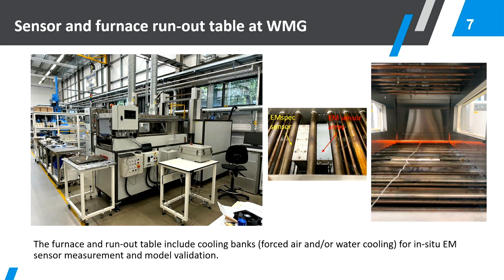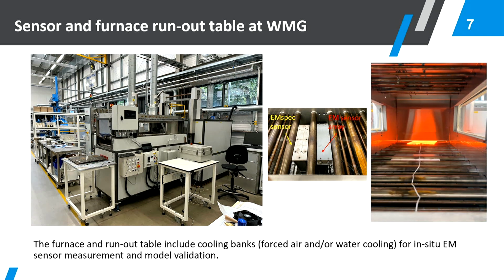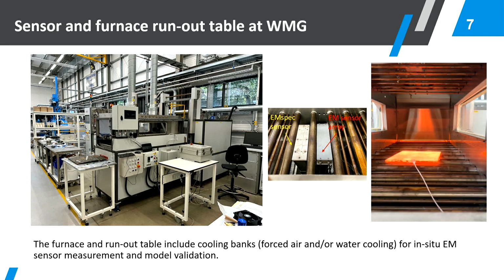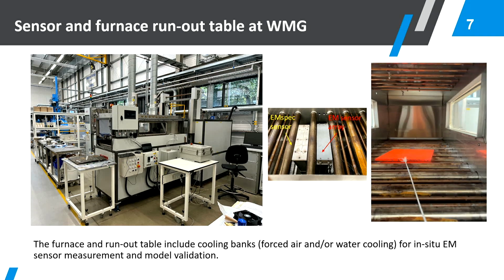We have done a series of tests in the lab at WMG. This is one of the pieces of equipment that we have, where we have a furnace and a run-out table. This is really trying to simulate what is happening at the run-out table at a steel mill, where you have the hot rolling, and then the steel comes out, and you can decide to spray water on or use forced air cooling for some of the rod product. So you control the cooling rates there.